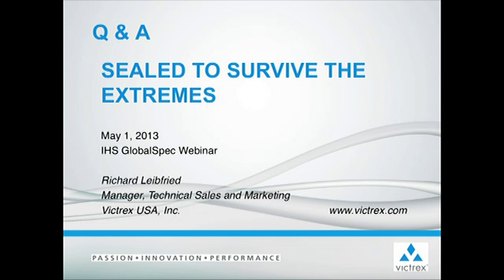Okay, our third question. What is the most common failure mode for PEEK in seal rings? We get this question often, and in our experience with thousands of sealing applications, it's rare to see catastrophic failures with VICTREX PEEK seals. However, a few of the failure modes we do see in rotating seals are excessive wear when high pressure or velocity take the material beyond suggested PV limits. In some cases, this is resolved by re-evaluating the best VICTREX PEEK grade to use in the application. For example, our new VICTREX WG series offers higher PV limits and extends performance life over standard PEEK bearing grades.